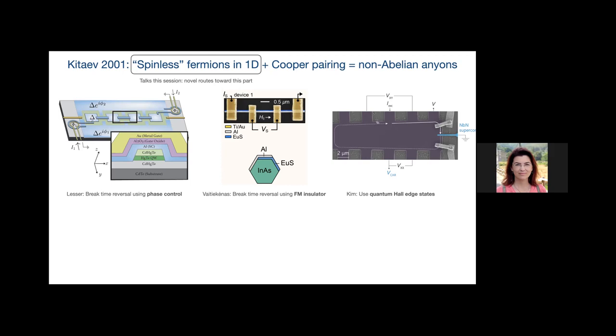Well, you saw probably in my transparency the case of the non-overlapping device, when there was no overlap between the europium and the superconductor. And there it definitely is much more difficult to get a topological transition. So the phase diagram had much smaller regions with topology, and the induced topological gaps were also much smaller. But it was not impossible, because at the end you could have a situation where the wave function spread basically all across the cross section and could get correlations from the superconductor in the regions where it is close to that, and also from the magnetic insulator. But of course, electrostatically, this was not very easy to find, and the induced gap was much smaller. The wave function was really much more spread. Whereas in the overlapping device, you have the possibility of having the wave function close to both the europium and the aluminum at the same time, and then the proximities are much higher. Okay, thank you.